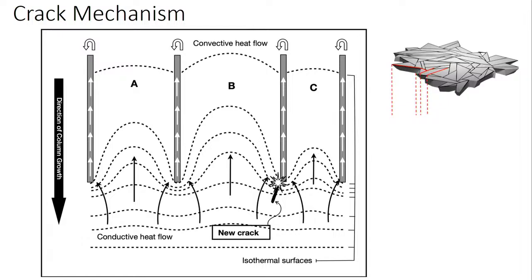Because of this unequal temperature distribution between the fat columns and the thin columns, the density of the isotherms at the face of the crack columns is different. This particular crack node is therefore acted upon by the thermal stresses of its neighboring columns, and in the next moment of its movement, it is obviously going to move in the direction in which it can release its thermal stress most easily, and that will be in the direction of the steepest gradient of temperature. So if there is greater crowding here, this crack, instead of moving down like this, will change its direction. We are looking at this mechanism which enables a crack which started as random to ultimately change its shape and become hexagonal. So that's what we are looking at.